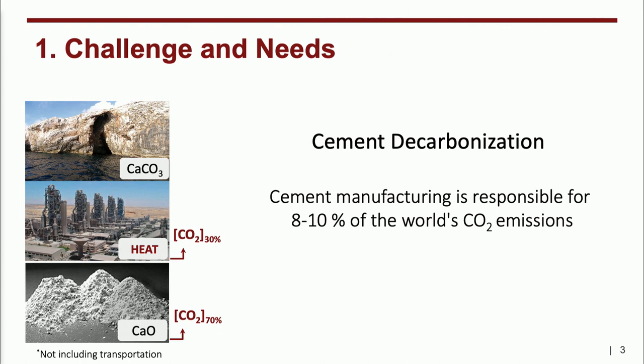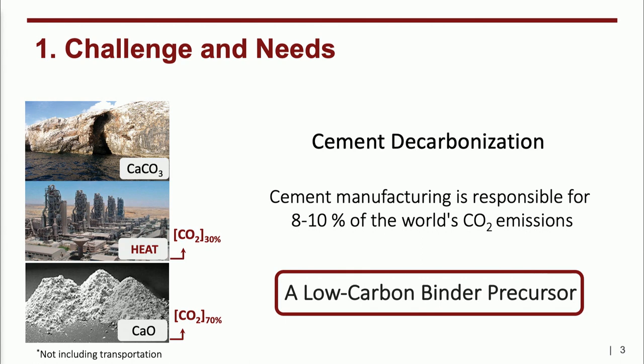The reason is that, if we neglect transportation, at least 1/3 of the CO2 comes from the energy that is used to calcine the carbonate rock, and then 2/3, or 70%, comes from the reaction that breaks down the calcite mineral to obtain the calcium oxide, or the lime. So from here, we can make a first reflection. If tomorrow we were to have the cleanest energy resource, we would take care of only 1/3, but we would still have to deal with reducing the remaining 2/3, the 70%. So for this, we need a different rock, and that's the role that geoscience plays. We need a low-carbon binder precursor.